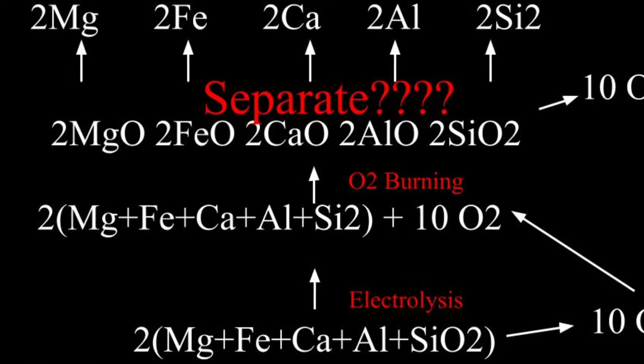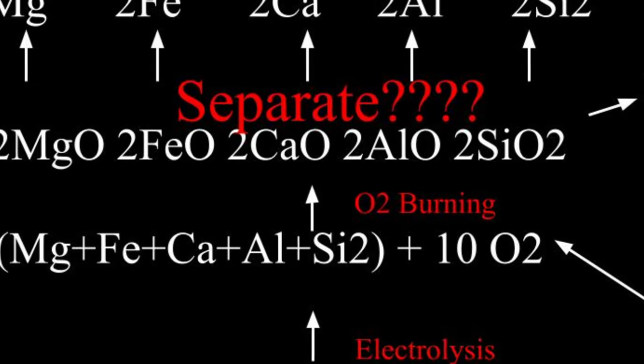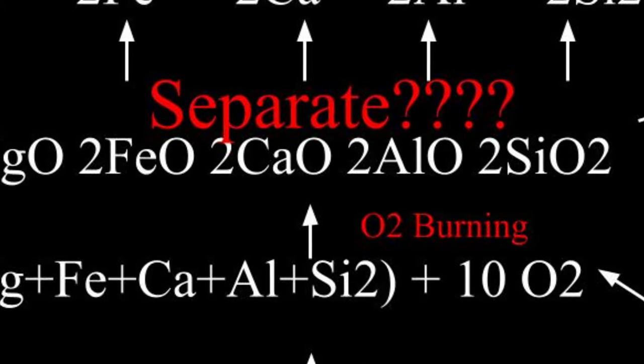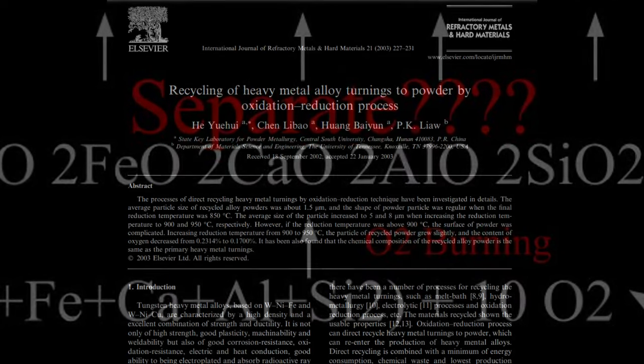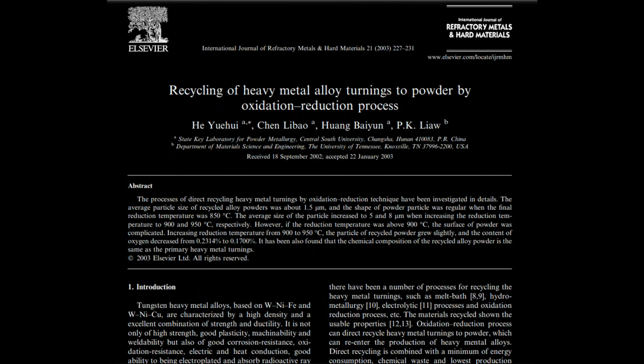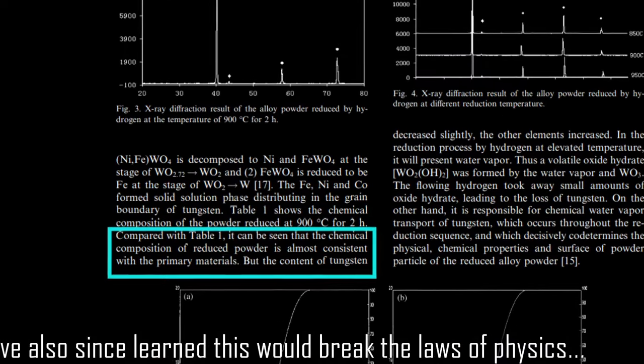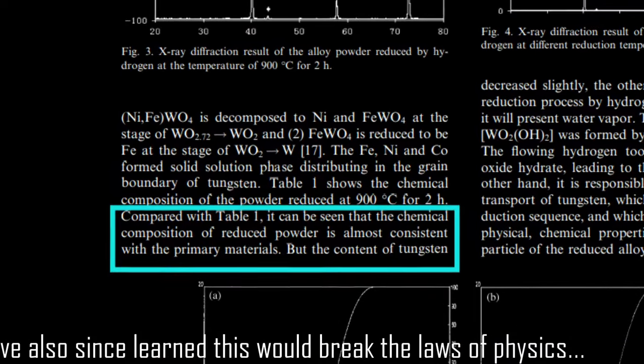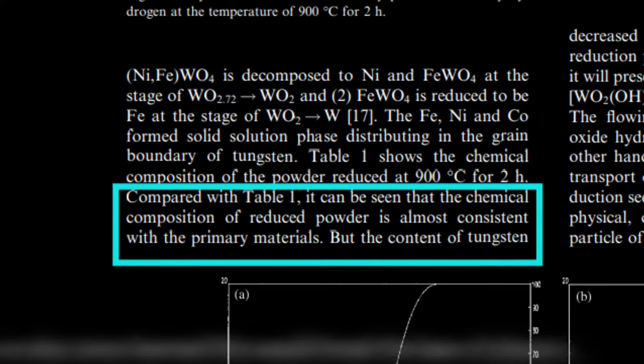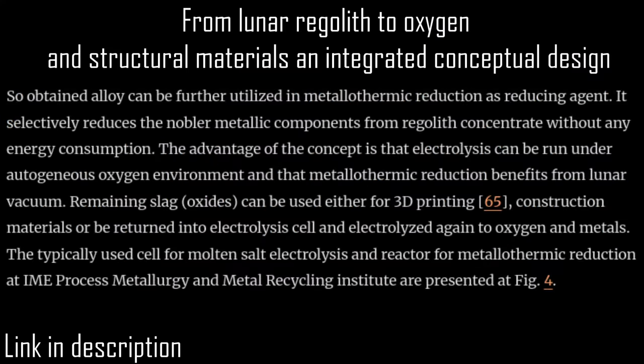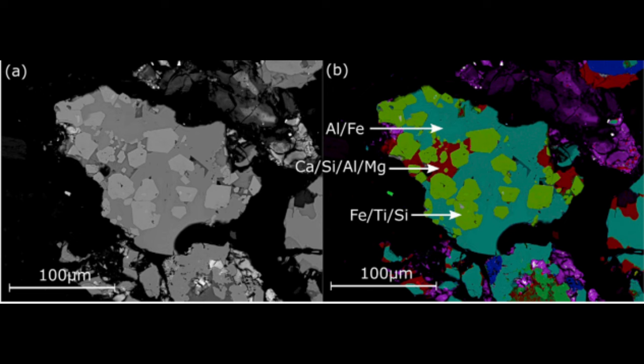But all of this is dependent on the extent to which the reformed oxides separate during combustion. Unfortunately, I wasn't able to find any info on this, but the one paper I did find that kinda did something similar for recycling tungsten heavy metal alloys found that the resulting compounds remained alloyed together. Not good. Another paper suggested just using the alloy itself to reduce the next batch of incoming regolith, and this is actually a pretty good idea. Basically, our alloy is made of metals bonded to themselves and each other, but they'd prefer to be bonded with oxygen. However, to do this, they'd need to steal the oxygen away from another oxide.